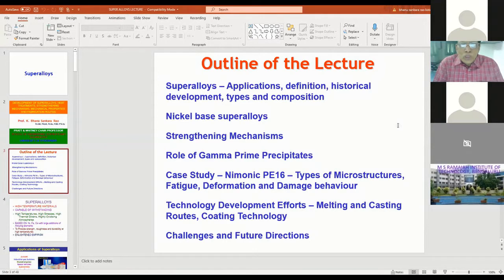The superalloys derive their strength from several phases. The microstructure consists of several phases. It depends on composition. So there are several strengthening mechanisms that contribute to the strength of superalloys at very high temperatures. The strengthening phases are known as gamma prime and gamma double prime, which will contribute strength in the matrix, and there will be solid solution strengthening in the matrix, and the carbides will be there on the grain boundaries to impart creep resistance at elevated temperatures.